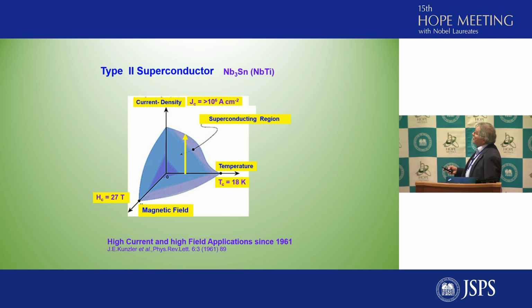And at elevated temperature far away from liquid helium. And they were able to produce very high magnetic fields, but only below this area which is given by these three parameters, below this surface, because as soon as you are approaching Tc, the current density would go down drastically. The same would occur if magnetic fields were applied to these materials.